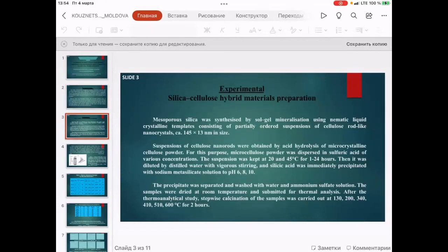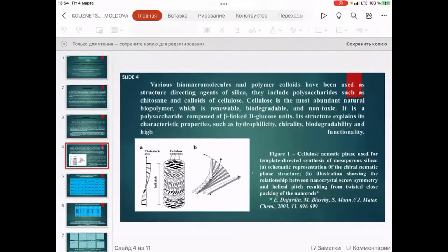Silica cellulose hybrid material preparation. Mesoporous silica was synthesized by sol-gel mineralization using the nematic liquid crystalline templates consisting of partially ordered suspensions of cellulose rod-like nanocrystals, 145 by 13 nanometers in size. Suspension of cellulose nanorods were obtained by acid hydrolysis of microcrystalline cellulose powder. For this purpose, microcellulose powder was dispersed in sulfuric acid of various concentrations. The suspension was kept at 20 and 45 degrees C for